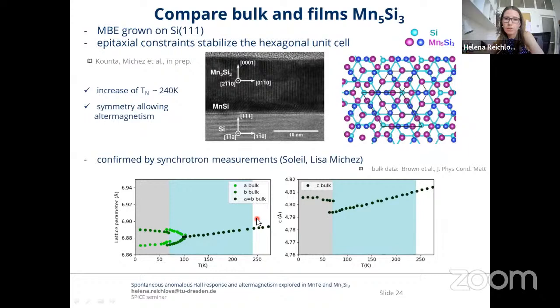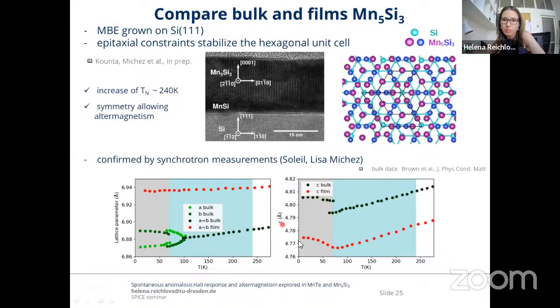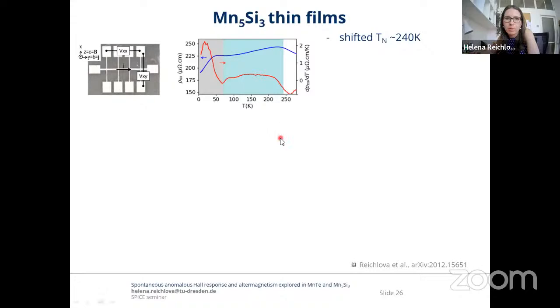The red dots are now our thin films. The c lattice parameter exhibits a similar change because this is the c direction, which is not constrained by the silicon substrate. However, the ab lattice parameter does not have the freedom to move because it's simply stabilized by the hexagonal pattern from the silicon. And therefore our films are hexagonal in the full temperature range. As I mentioned, the strain stabilization also led to the increase of the Néel temperature.